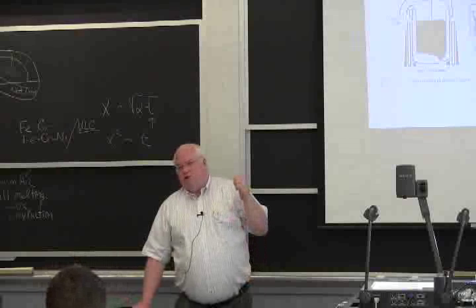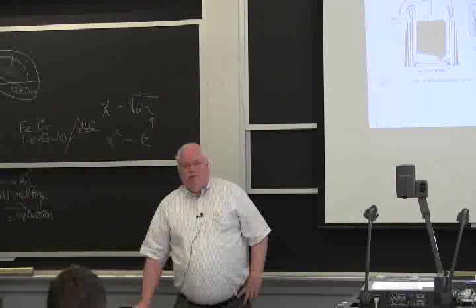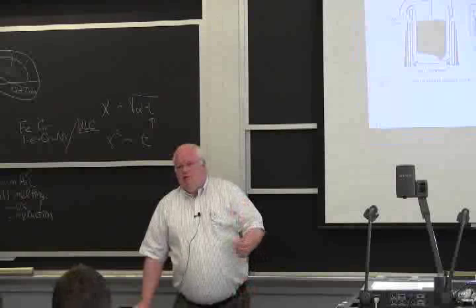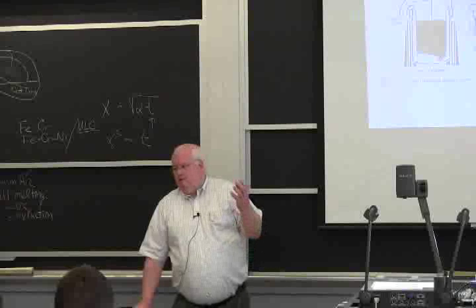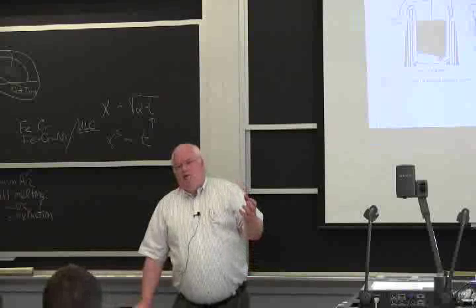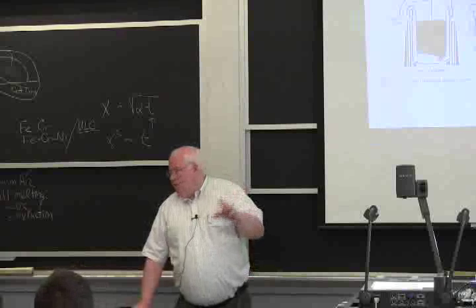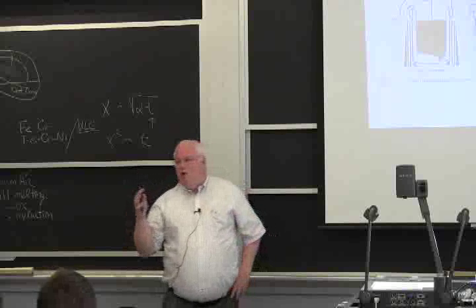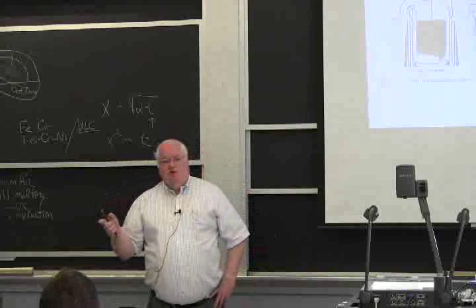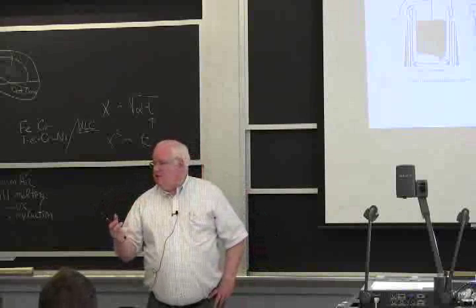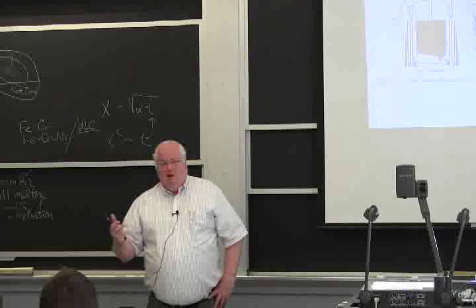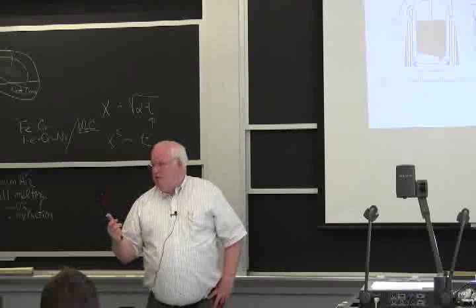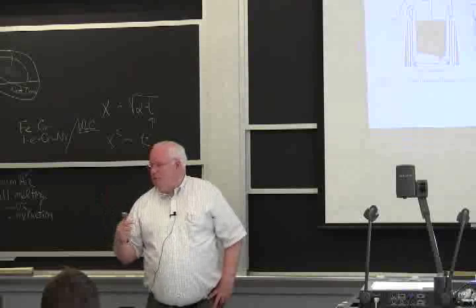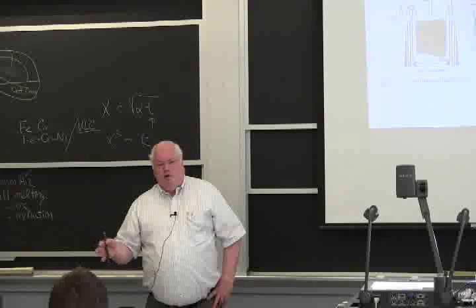But because of some basic research that was done here in the basement of Building 8, they were looking at what happens when you bubble argon through the bottom of the steel bath. Instead of having a bubble in your molten bath of steel of 1 atmosphere of carbon monoxide, if most of your gas is argon, the partial pressure can be 1/100th of an atmosphere of carbon monoxide. If you just look at the thermodynamic equilibrium, you can drive your carbon down very low.